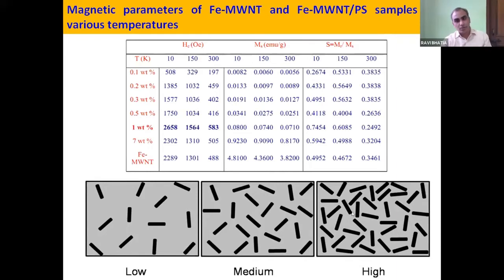So in this case, exchange interactions are more dominant. In the low samples, this is 0.1, 0.2, 0.3, all these samples I'm talking about now, they are too far apart that dipolar interactions are more efficient than the exchange interaction, because in the exchange interaction, the spins need to be nearby. So here only the anisotropic properties of iron nanorods appear, and in the high case both exchange interaction and dipolar interaction appear. And in the medium, which represents the 1 weight % sample, here the dipolar interactions are maximum, more significant than the exchange interaction.